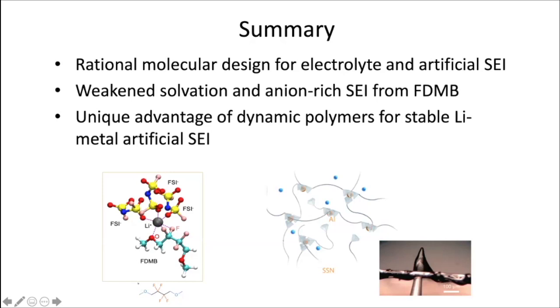lead to anion enriched SEI. This is the reason we think is enabling stable cycling. And then in terms of the artificial SEI, the approach of using dynamic polymers combined with chemistry to design a stable polymer network is the key, we think, to achieve a stable lithium metal artificial SEI.